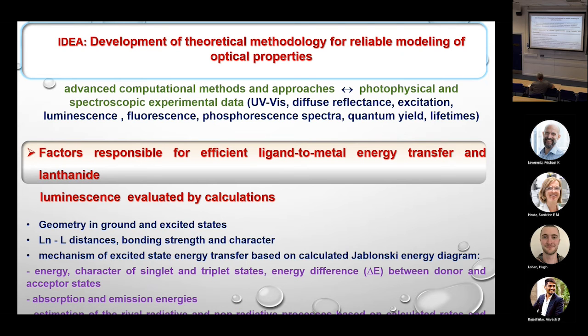Also, we can predict the mechanism of excited state energy transfer based on the calculated Jablonski energy diagram. Very important is to predict the energy of the excited state, character of singlet and triplet states, the energy difference between singlet and triplet for intersystem crossing, and also the energy difference between donor ligand and acceptor energy of the lanthanide ion.